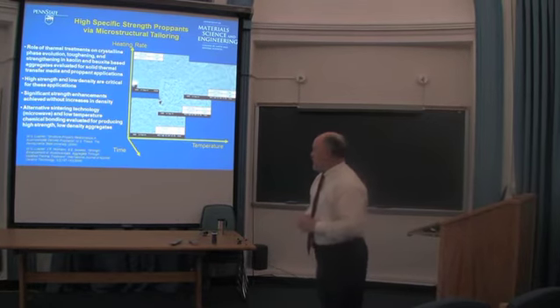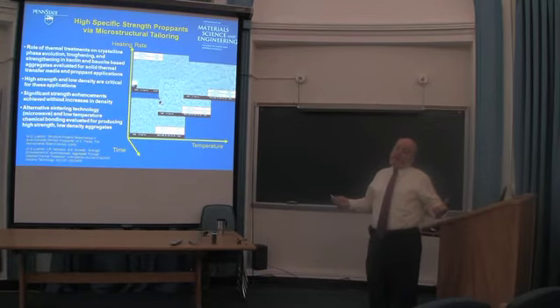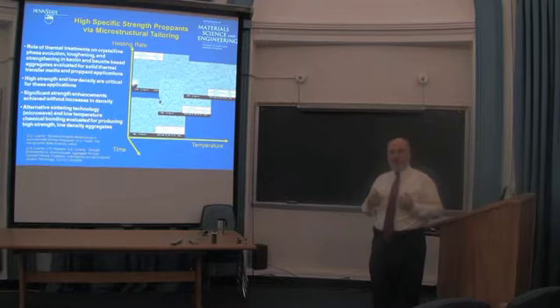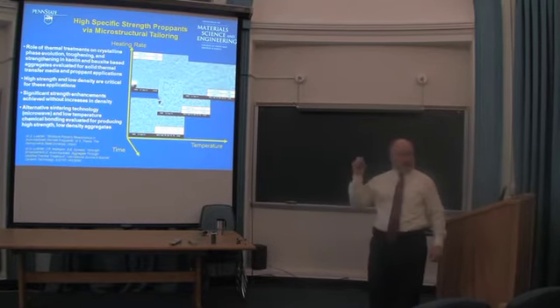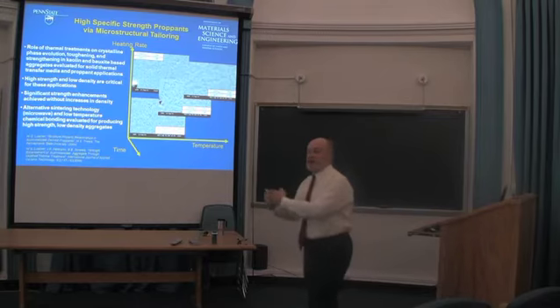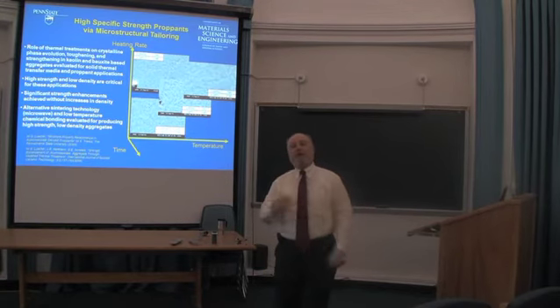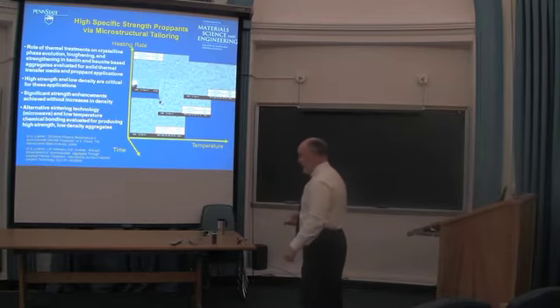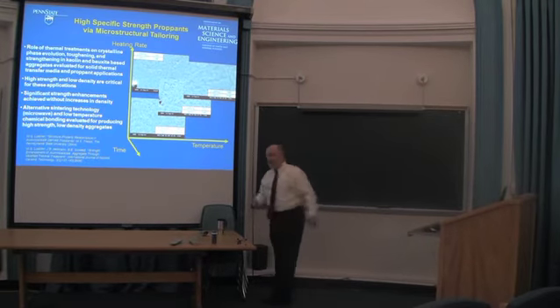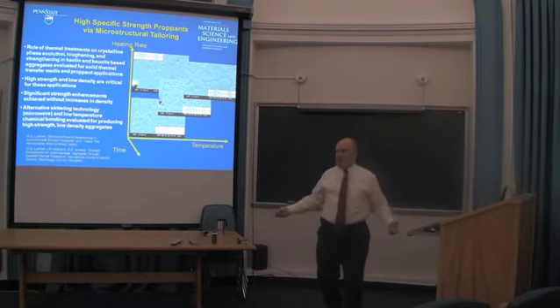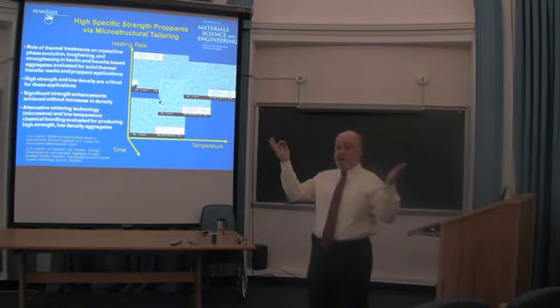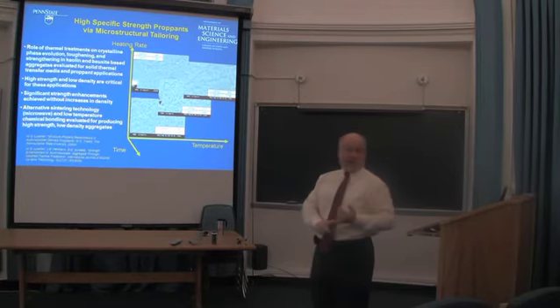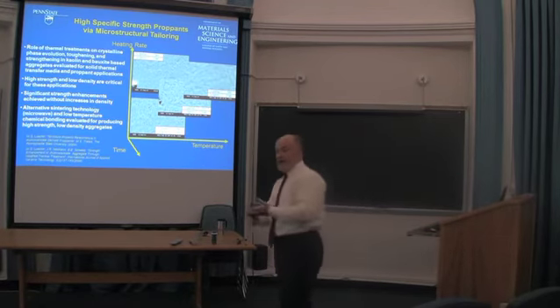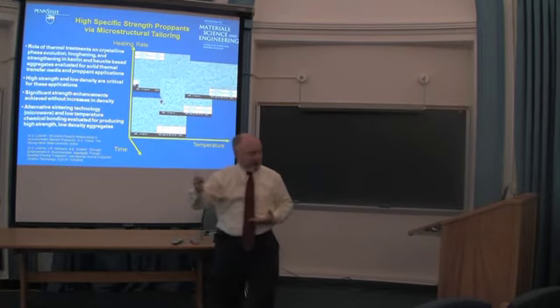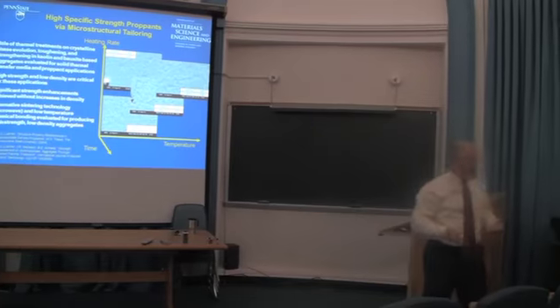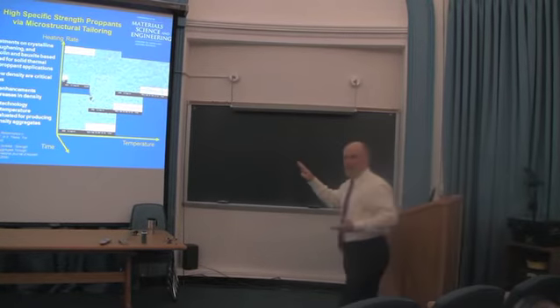Okay? Well, what we were interested in knowing was, okay, given a certain ore, bauxite ore, is there something we can do to tailor microstructure and to tailor chemistry via changing the time at temperature during the sintering process to give you better properties? So we spent about 5 years working on that. And what we were able to demonstrate was that what the proppant community hadn't looked at, but the refractories industry did for years, was that all the phase equilibria related to steel refractory slag interactions plays a role here. All the work Arnulf Muan and Albert Osborn did at Penn State Geosciences is pertinent here.